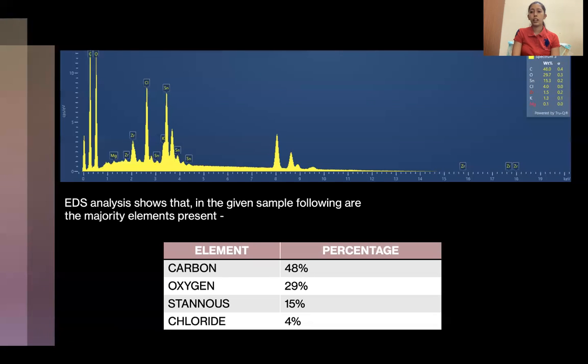Apart from that, EDS, which is energy dispersive spectroscopy, analysis was done in the given sample as shown, in which it was seen that carbon was 48%, oxygen was 29%, stannous was 15%, and chloride was 4%. This shows the elements which are present in the nanoparticles, which was stannous chloride, apart from the basic carbon and oxygen.